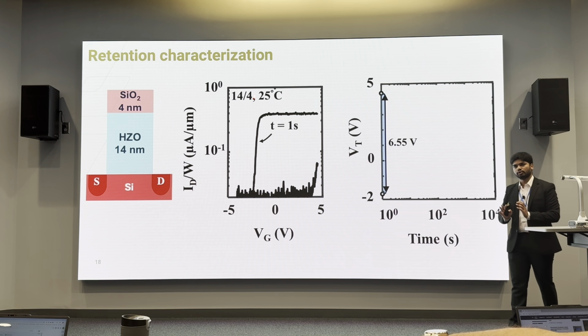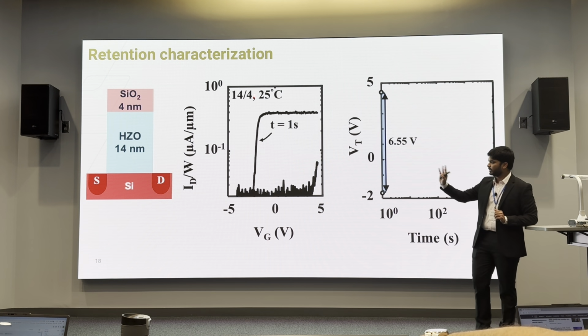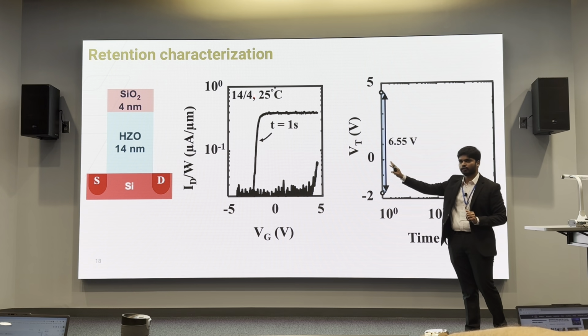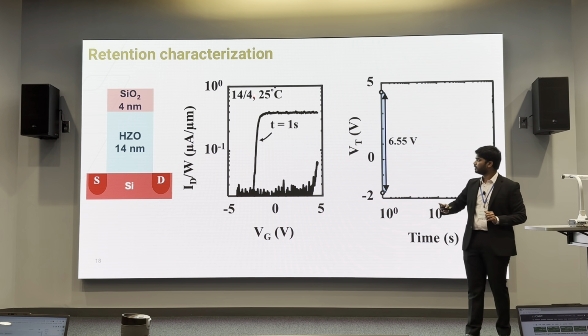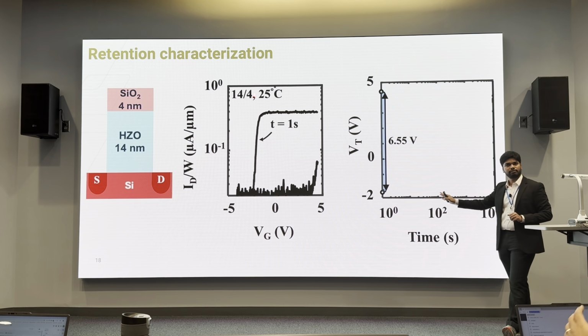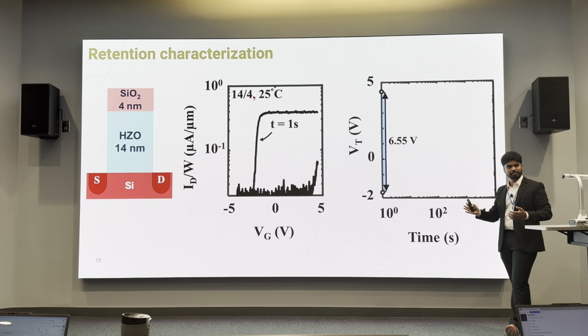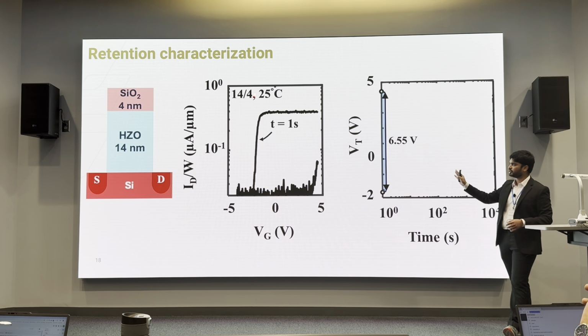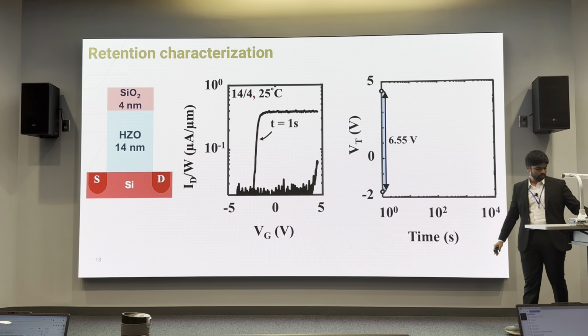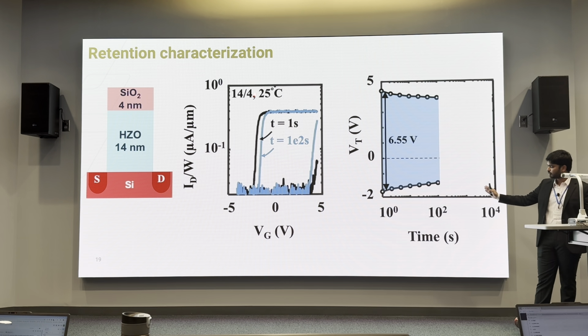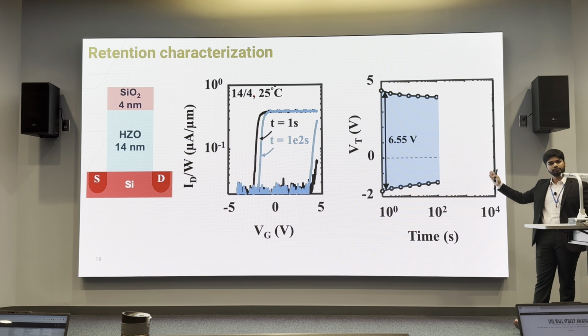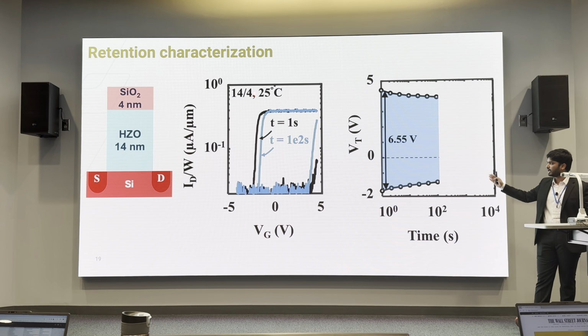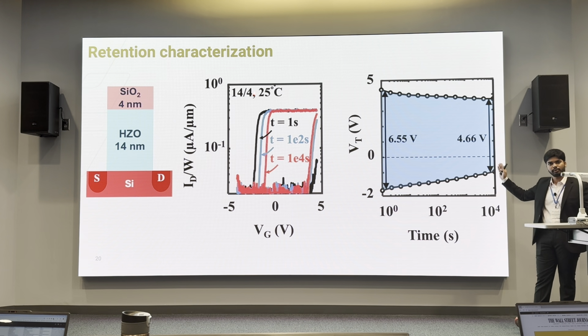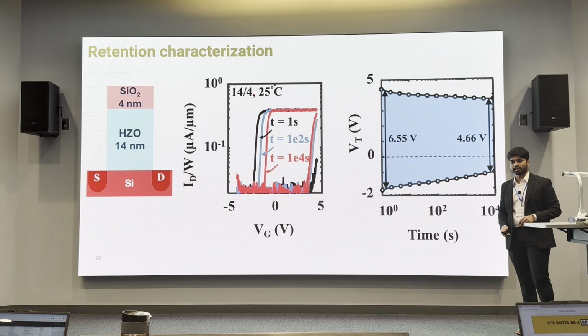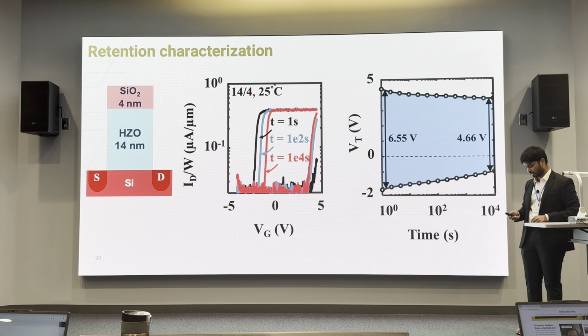So let me walk you through how retention measurements are done. We take the standard FEFET 14-4 with a silicon dioxide layer at the top. We start out with a 6.5 volt memory window, which is an enhanced memory window. This is done at room temperature, and that is the initial memory window. And we let it stay for about 100 seconds. We see a 14 to 15% degradation in the memory window already in just 100 seconds. And after 10,000 seconds, we see that the memory window has dropped 29 to 30% down to 4.66 volts.